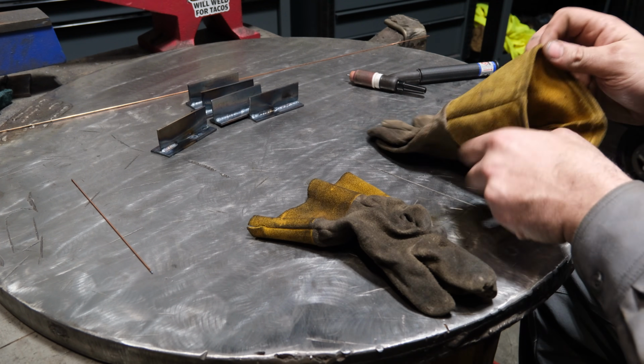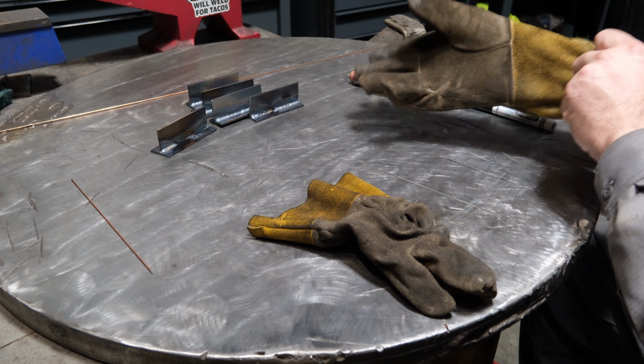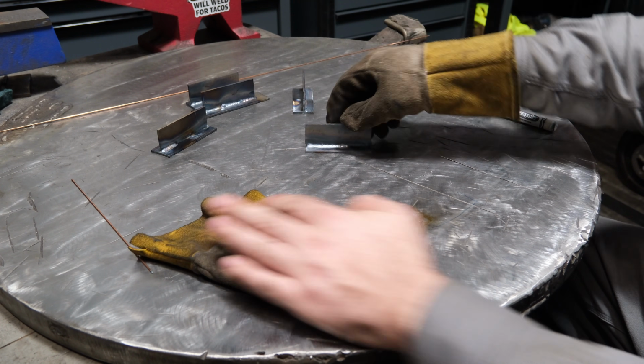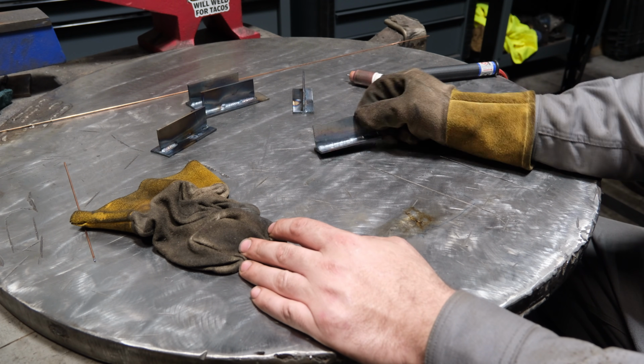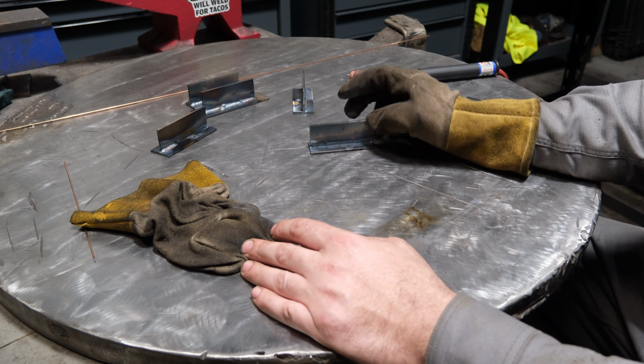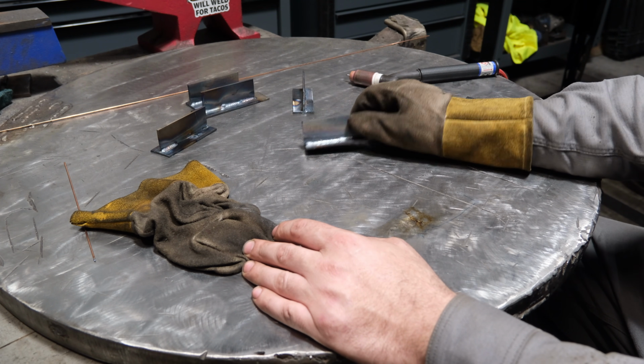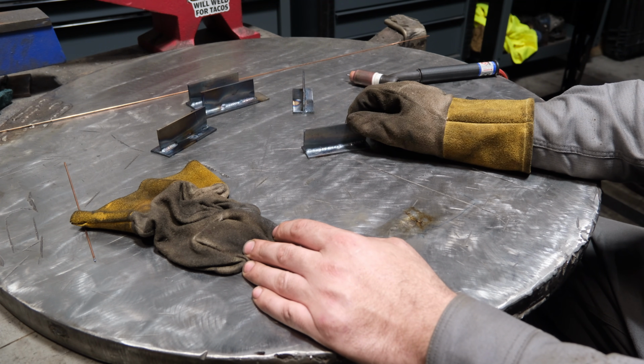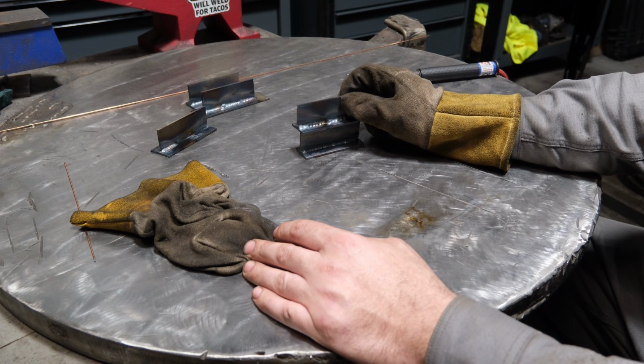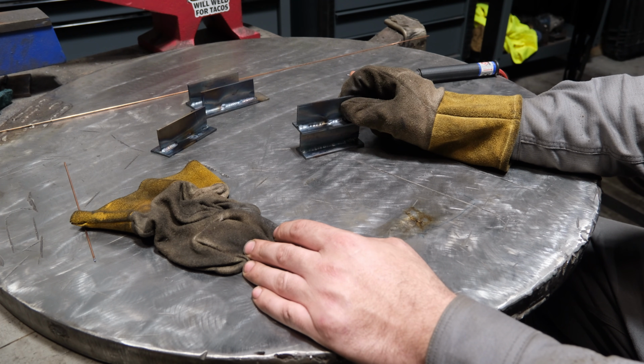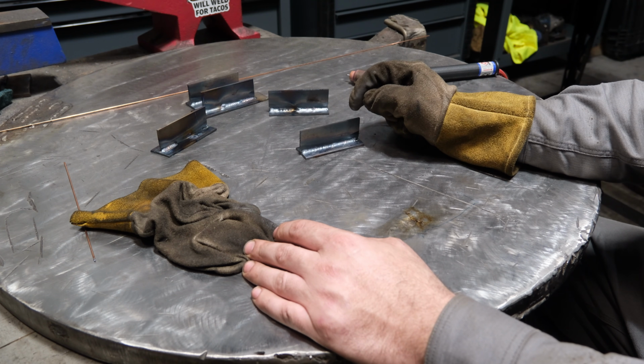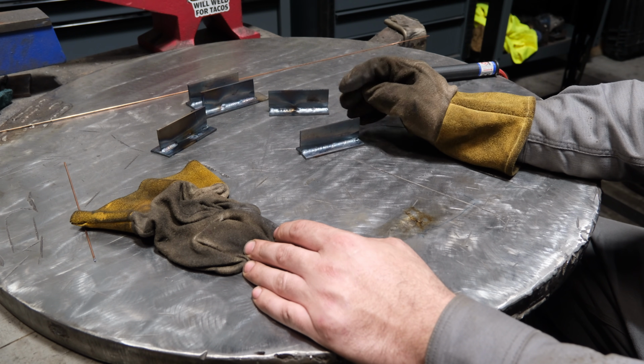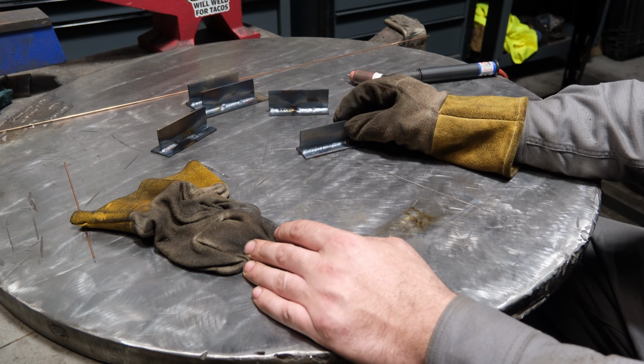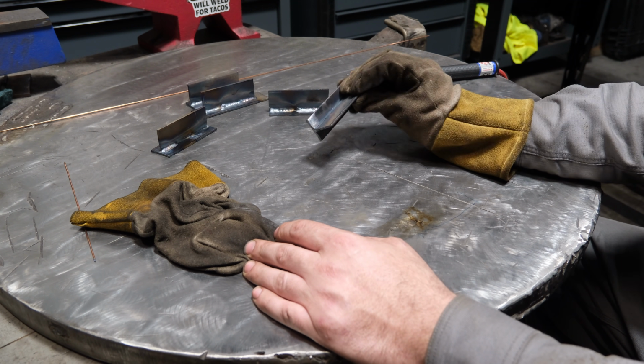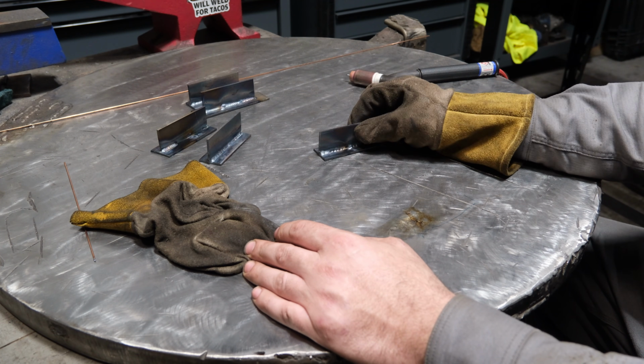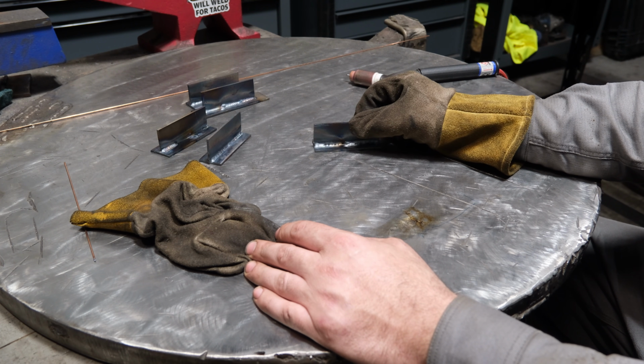Now, this is probably still too hot for me to hold. But something I didn't mention, when it comes to material: if you just do stuff like this and then the back gets all oxidized and welds poorly, how much practice are you really getting? Well, the smarter thing to do would be to weld a flat plate on the top like this and then keep going to where you more or less have 4 fillet welds, 2 on clean metal, 2 on not so clean material, rather than just taking this and throwing it in a round file. I mean, it's a waste of material, so that'll save you a little bit.